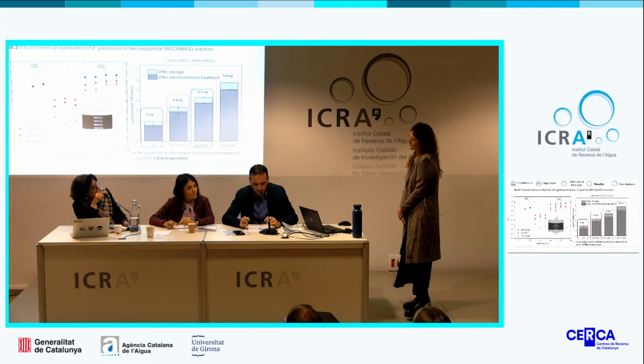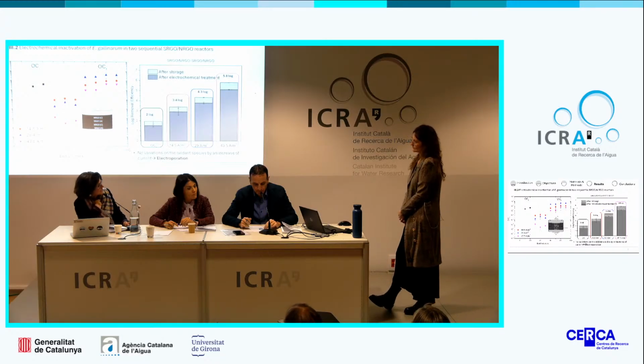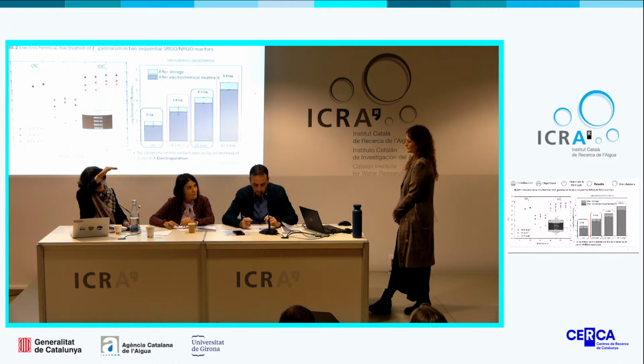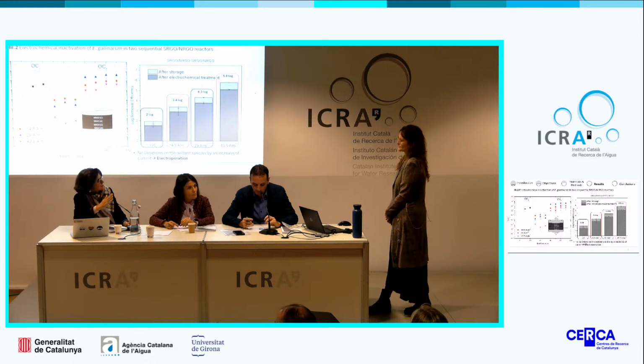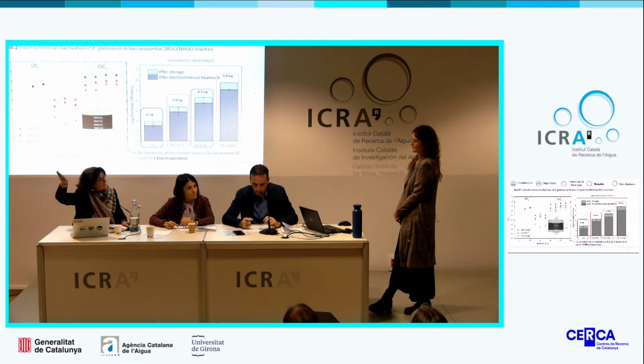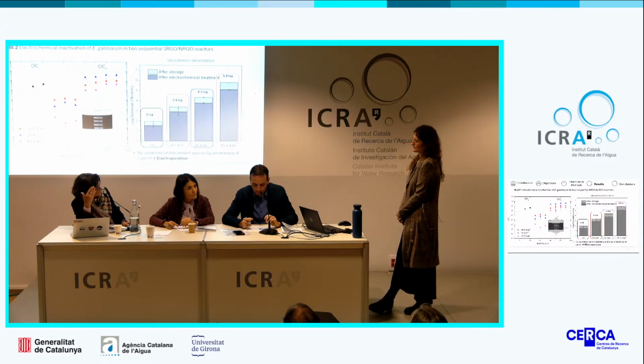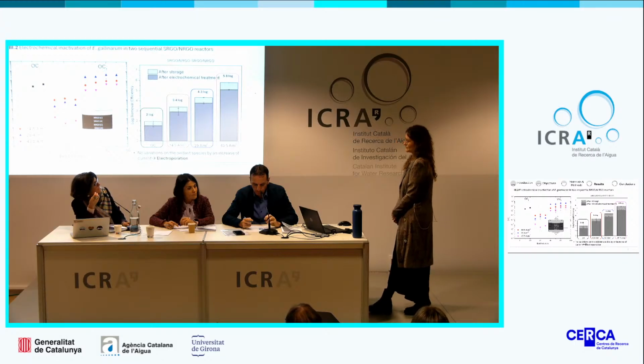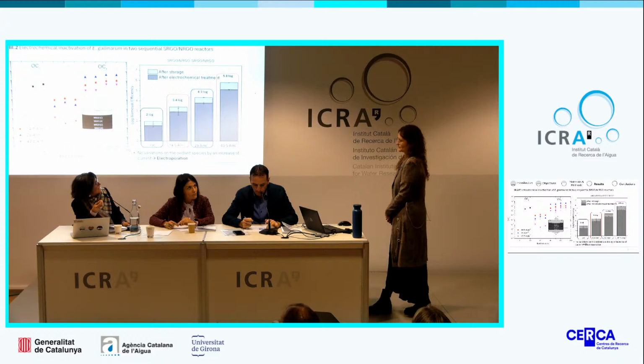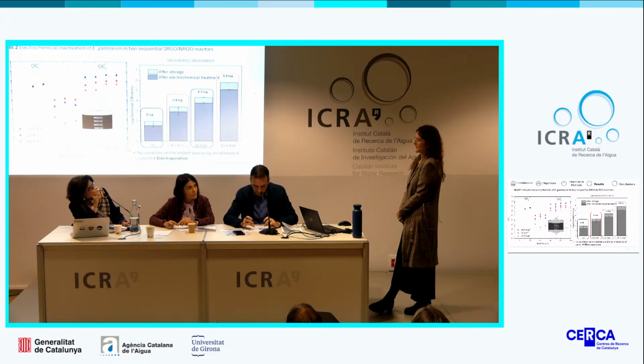Because today you said that there is adsorption, so there is electron transfer, in particular with sulfamethoxazole. And in my experience using boron doped diamond with sulfamethoxazole, on linear sweep voltammetry we have a very high peak, which is very separated from the oxidation of the solvent. So it means that direct electron transfer is possible with sulfamethoxazole, and there is no adsorption in your case. Okay.